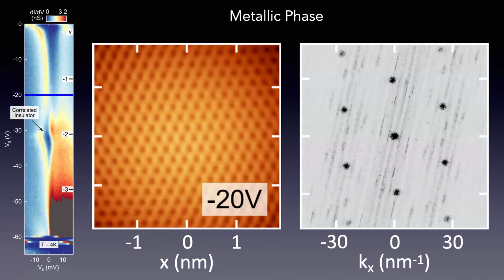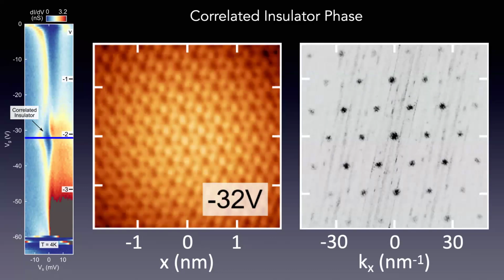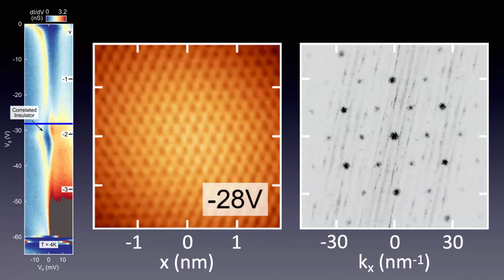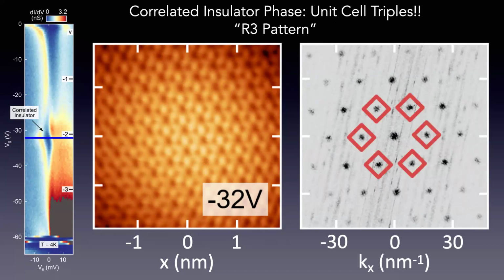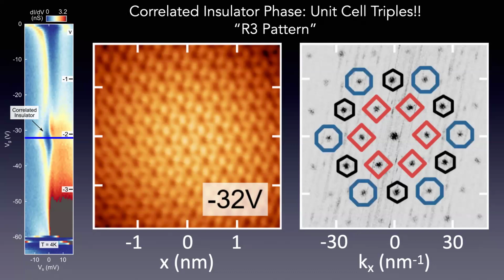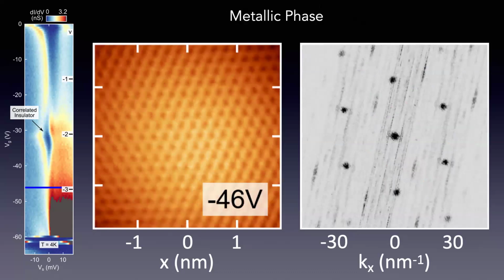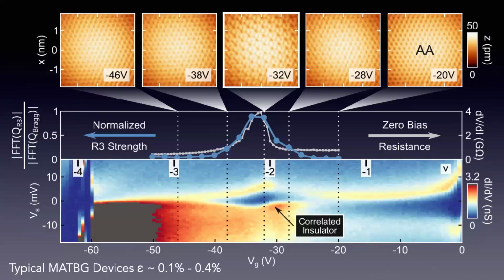Now, this is a very small field of view. And as you start going into the insulating gap, you begin to see other features. And you see that there's this tripling of unit cell that happens from all these graphs. The tripling of unit cell happens by these red peaks, and it's so ordered that you can see even higher order peaks. And if you exit this insulating gap, you can correlate the appearance of this tripling of unit cell with the appearance of this insulating state.